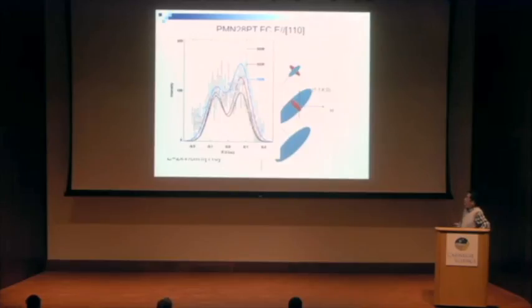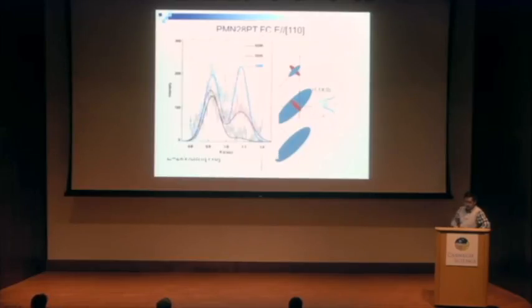For the scan near the 100 Bragg peak, we see a clearly asymmetric two-peak structure, and the right peak from the blue wing is clearly stronger than the peak from the red wing. And for the scan near the 110 Bragg peak, the weak peak from the blue wing is enhanced by the field, and at low temperature around 100 K it is almost similar in intensity compared to the peak from the red wing.